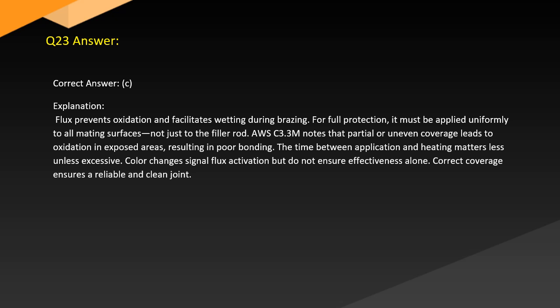Answer. Correct answer: C. Explanation. Flux prevents oxidation and facilitates wetting during brazing. For full protection, it must be applied uniformly to all mating surfaces, not just to the filler rod. AWS C3.3M notes that partial or uneven coverage leads to oxidation in exposed areas, resulting in poor bonding. The time between application and heating matters less, unless excessive. Color changes signal flux activation but do not ensure effectiveness alone. Correct coverage ensures a reliable and clean joint.